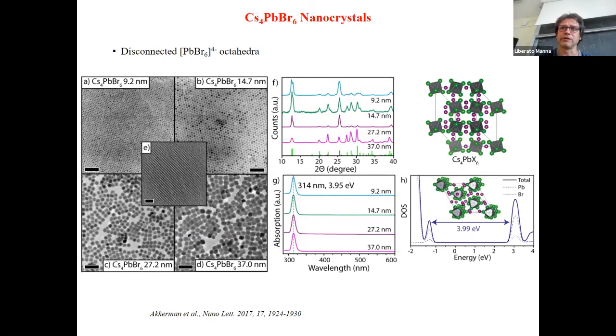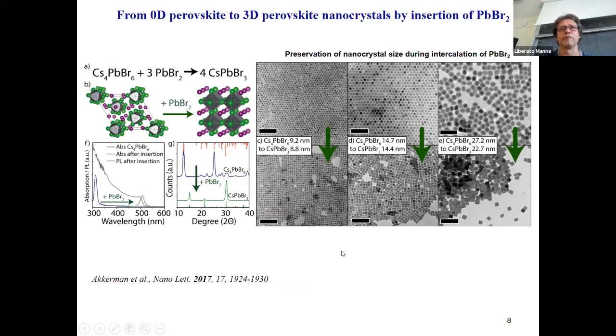Now, let's look in a little bit more detail at some of these reactions. So, for example, Cs4PbBr6 nanocrystals are insulators because they are formed by isolated lead halide, for example lead bromide 6, octahedra. So, for example, if you make nanocrystals of different sizes, the optical absorption is always the same. There is no quantum confinement effect. It's a high band gap material, but then you can use this to form a perovskite by intercalating lead bromide, for example. And as you can see, the size of the nanocrystal is preserved, although there is a change in the crystal structure.